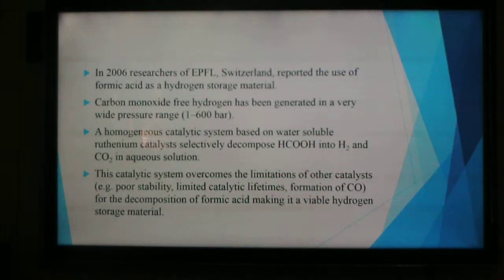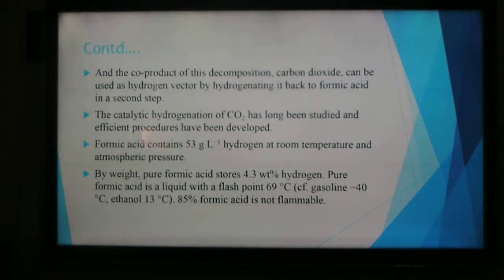Next, formic acid. Carbon monoxide free hydrogen has been generated in a very wide pressure range. So a homogeneous catalytic system based on a water soluble ruthenium catalyst selectively decomposes HCOOH, that is formic acid, into hydrogen and CO2 in aqueous solution. So what we can see is it stores 4.3 weight percentage hydrogen. Pure formic acid is a liquid with a flash point of 69 degrees C. 85% formic acid is not flammable.